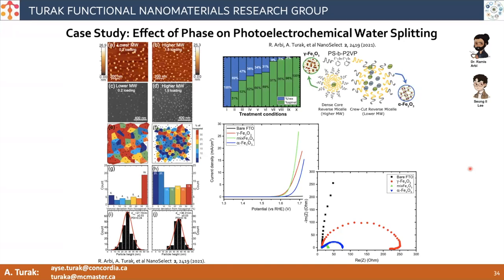Without changing the particle size, we could actually just change the structure by tuning the conditions a little bit. And this again allowed us to access, with the new data that we got with the seminar, we were able to see that there's still a difference if you have one pure phase versus the other phase with roughly the same size particles. So without really trying to uncouple those two usually convoluted systems.